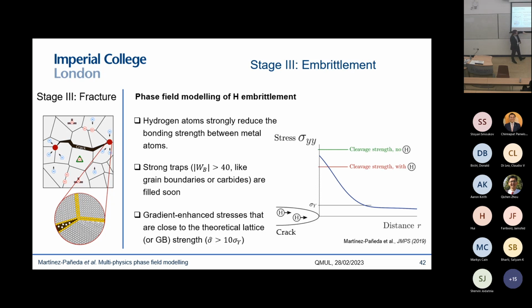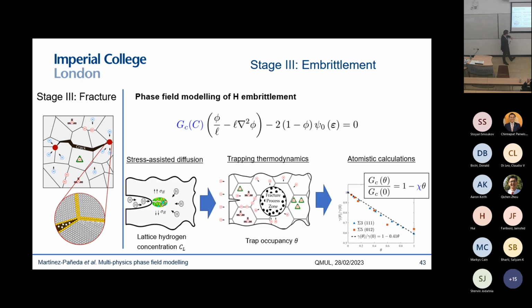But the moment you bring the hydrogen in, you lower your cleavage strength, and then these two lines cross, and you have a story. You have a model that, without any fitting parameters, can capture this transition from ductile to brittle failure. This comes very easily and naturally in a quantitative fashion in the phase field model, because as you can see here, we are solving for the diffusion problem, so we know how much hydrogen we have in our lattice, where and when, in which regions of the component.